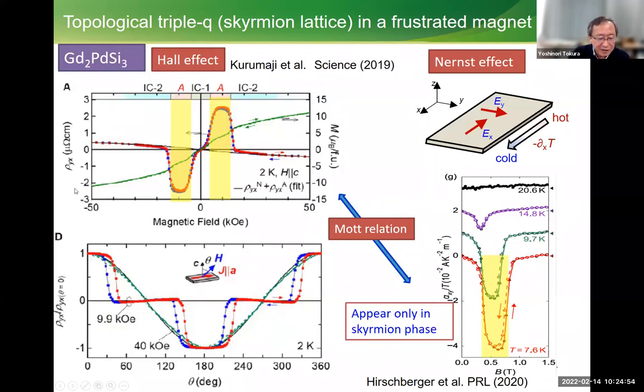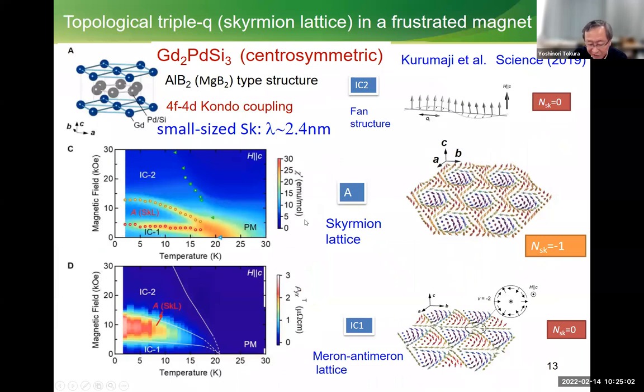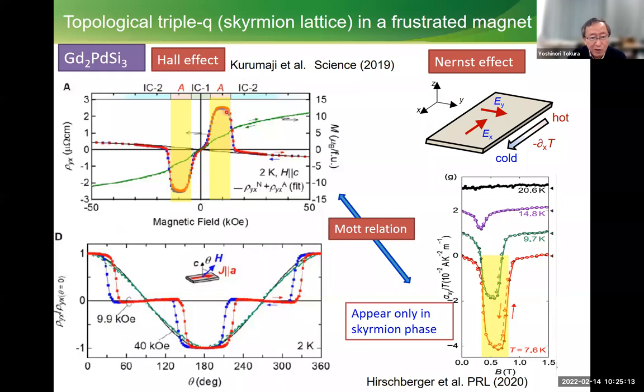Again, this is the Hall effect, and this is the magnetic field. By changing the magnetic field along this direction, we observe the rather flat-topped features again. And this is nothing but the scalar spin chirality induced emergent magnetic field, it's just quantized. And so it shows a huge effect as compared with the conventional anomalous Hall effect. The anomalous Hall effect is not so small, but this topological Hall effect is so large.